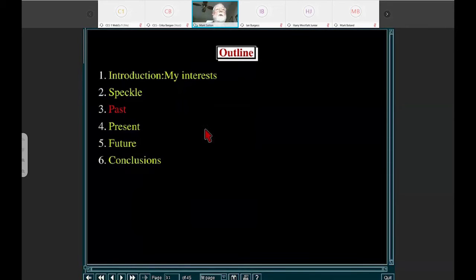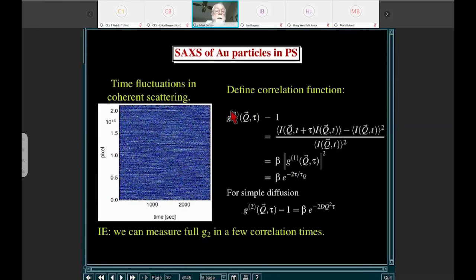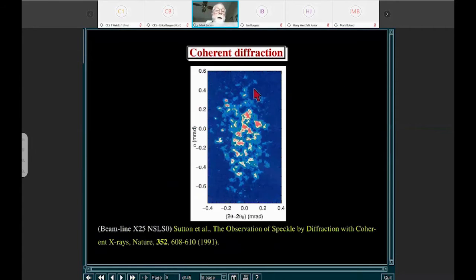With these new MBA lattices, everybody's going to be seeing speckle whenever they're looking at diffuse scattering, and so they need to consider mechanisms for getting rid of it. So one of the mechanisms for getting rid of it is to basically make the beam size so big that the speckles overlap in your detector. So your detector pixels are much, much bigger than your speckles. And basically any mechanism you have to average away the speckles gives you back the normal incoherent scattering.